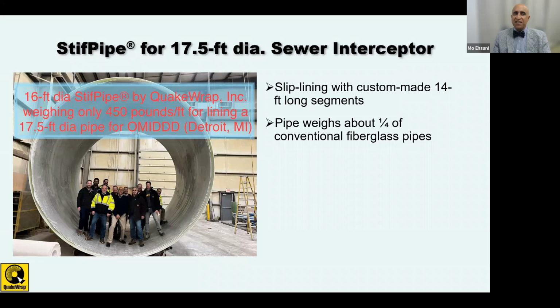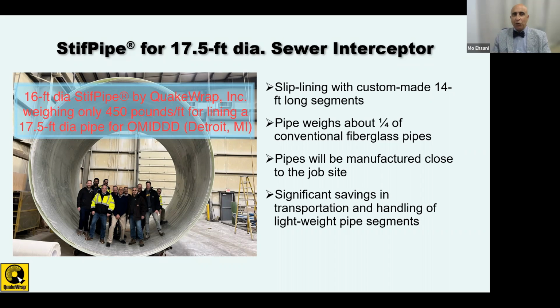And we are making these 16-foot diameter pipes and slip lining them into the 17.5-foot diameter tunnel and then grouting around the annular space. The unique thing, a couple of things to point out, is that this pipe weighs only 450 pounds per foot, even with this huge diameter. So the entire piece that you see here, about 14 feet long, is only roughly 6,200 pounds in weight. So it's very lightweight. And the other thing is that this technology allows us to make this pipe about an hour away from the project site.